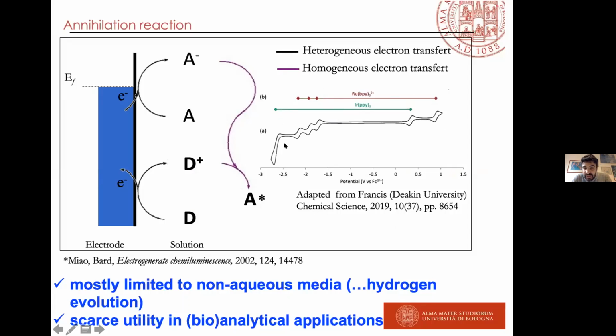Here I take this very nice picture from Francis in this very nice work. As you can see clearly here, you have to move to the oxidation potential that is around 1 volt and to a very negative potential that is around minus 1.5. So you need very aprotic conditions, and you can do that mainly only in acetonitrile or in THF, for example. So you need non-aqueous media, otherwise you will have the hydrogen evolution reaction, of course.